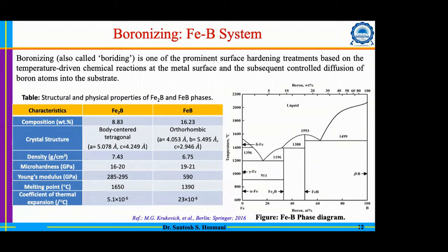Density-wise, Fe2B is denser compared to FeB. Hardness-wise, both have almost the same hardness, roughly about 20 GPa. Young's modulus is significantly different, and FeB is quite stiff compared to Fe2B. That is also one of the criteria you can imagine for why there should not be two layers together. Stiffness is one issue, and the second important issue is the coefficient of thermal expansion. The coefficient of thermal expansion of both the borides is entirely different, and that is also a critical issue.